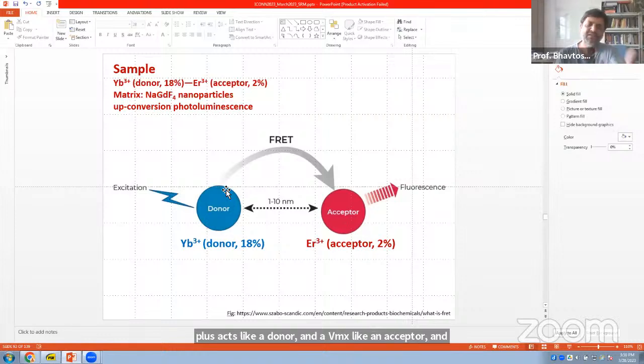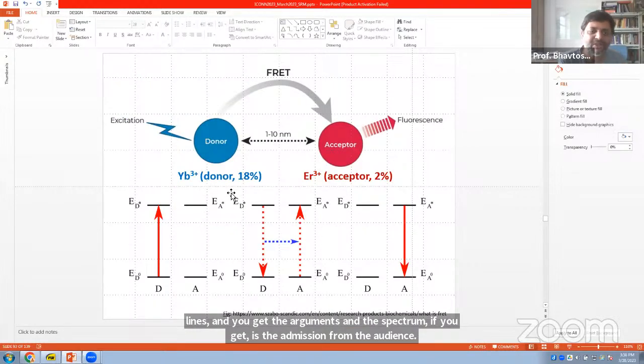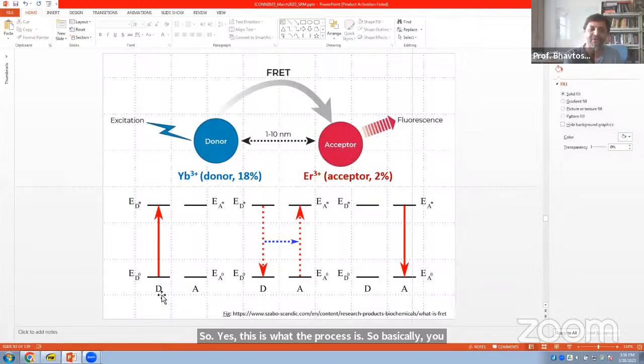You can excite the ytterbium ions, and these also work because there are 2-photon excitations, so you get enough conversion, but that's not very important for our purpose here. You excite the ytterbium ions and you get the erbium emission spectrum. So you first excite the donor atom, and then there is a resonant transfer of energy from donor to acceptor, and then the acceptor radiatively recombines and you get the fluorescence out.